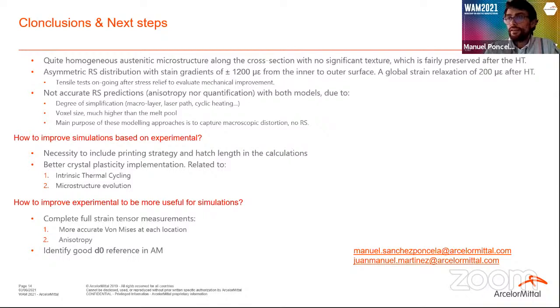So I conclude the talk, summarizing and doing a wrap up of everything we were explaining. So first, we propose a heat treatment for 316L in SLM that is good for reducing the residual stresses without modifying the microstructure much. That is what we wanted. In this line, we are now running some tensile tests on the specimens after this heat treatment to compare the mechanical behavior as built with the one after the heat treatment.